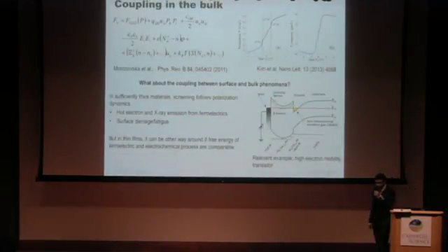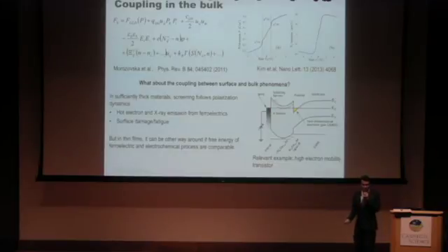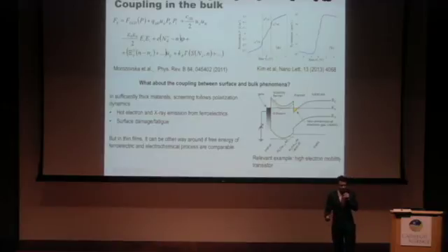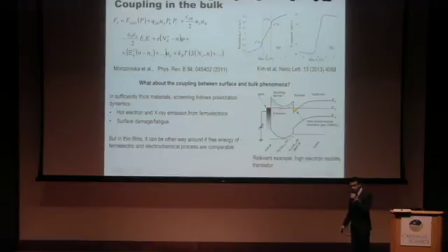If you look at bulk ferroelectrics, you can pretty much write Landau expansions and predict properties pretty well with current Landau theory. And so you can go ahead and add these terms. In general, you don't have to worry about the surface so much because, as I said before, the bulk polarization energy is so much higher that the surface really has to follow whatever the bulk does. So it's not so important when you're looking at single crystals to look at these effects. But we're in the thin film session, and when you go to 30 nanometers or thinner, what we find is that the surface electrochemical processes become on the order of the same energy scales as the bulk polarization energy, and so you have some very nice mixed states that form, which I'll get into in the next few slides.